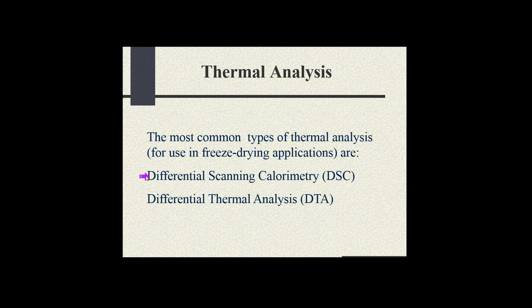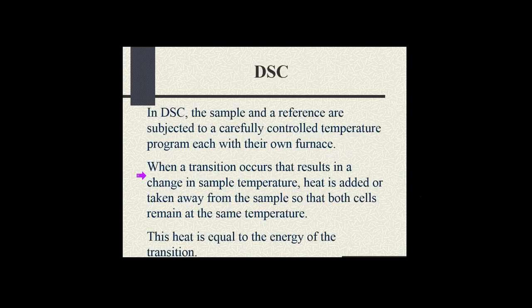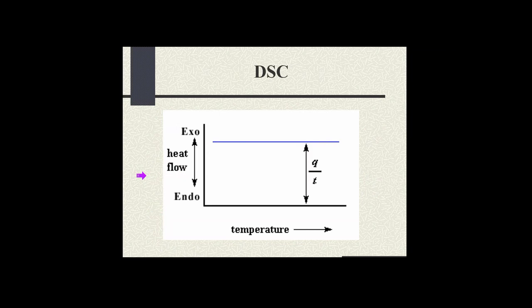Again, differential scanning calorimetry. They also make a modulated version that we can use mostly for solid materials or materials that are very complex and maybe have overlapping thermal events. So basically, we take our sample. Now, this would be just like we were going to take the liquid and put it in the freeze dryer, so everything's got to be the same. So we take the liquid, put it in the sample pan. We put an empty pan as the reference pan and cool these down and warm them up.